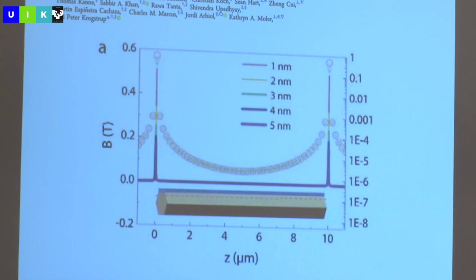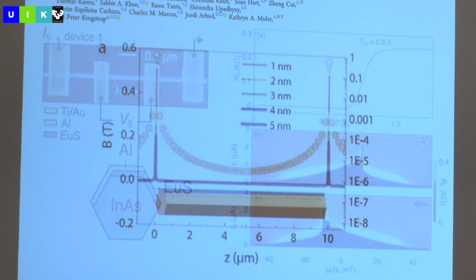And this is, if you remember how magnetic material behaves, magnetic fields come out of the ends. They don't exist near the middle. Here's a simulation where you measure the magnetic field. This is for different thicknesses, but what you can see, this is a log scale on the right, but let's just look on the linear scale. The only place where there's any appreciable magnetic field, actual B field, is at the ends of the wires. Everywhere along the wire, the B field is actually 0, even though the superconductor thinks it's in 4 Tesla. There's no magnetic field there. So this is a really remarkable physical system.